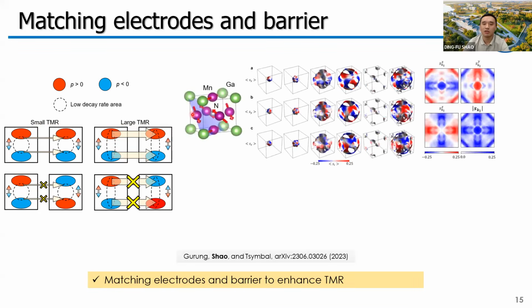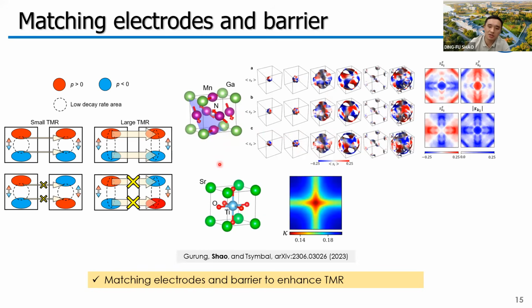So for example, we have such a non-collinear antiferromagnetic metal, manganese gallium nitride, which has well spin split Fermi surfaces. If we integrate the spins on the Fermi surface along the z direction, we can get the distribution of the spins on the conduction channels in the 2D Brillouin zone. We find that this distribution has a cross pattern. This reminds us that in the widely used barrier material STO, the slowest decay rate area also has a cross pattern.